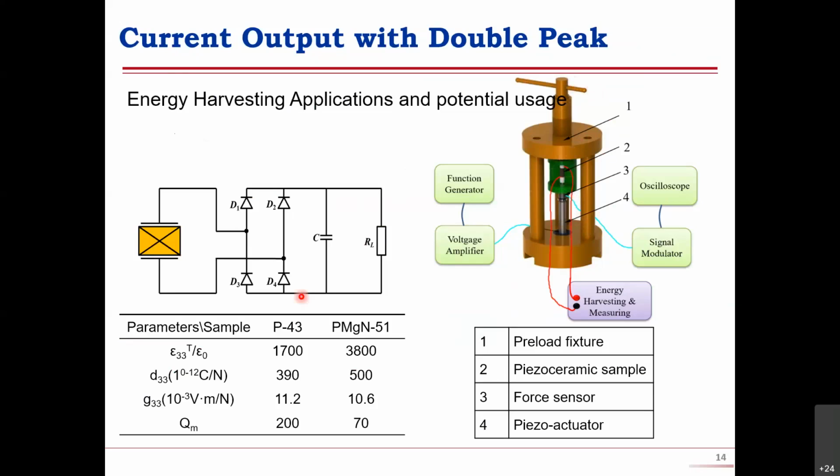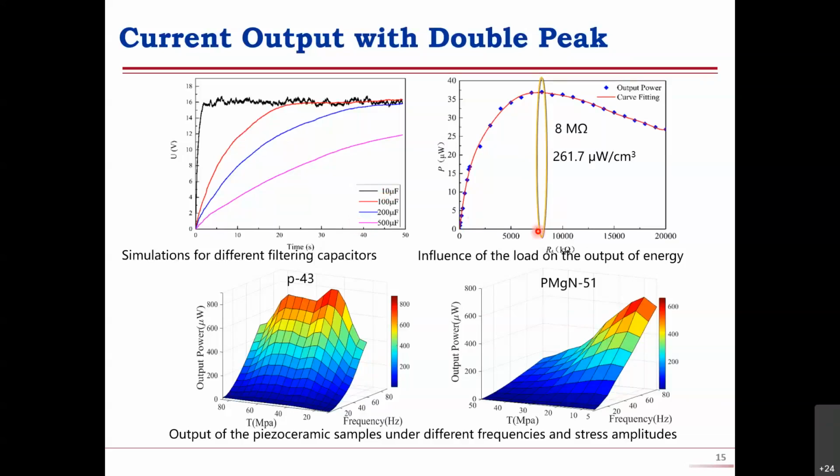And we use a standard circuit to first find the optimal load for this system, and then we apply different frequencies and different preloads to this piezoceramic, and we take 80 hertz excitation as an example.